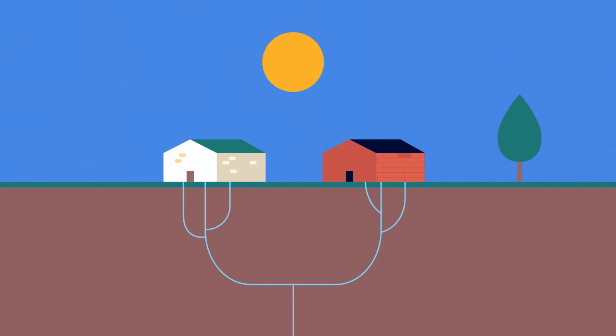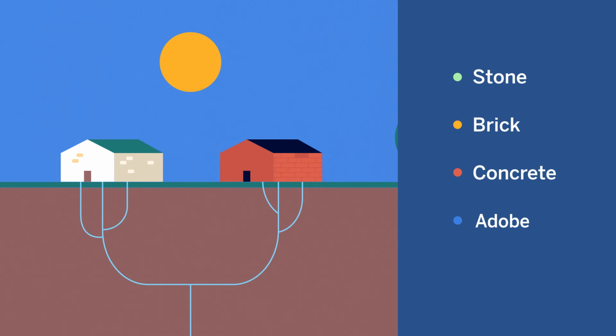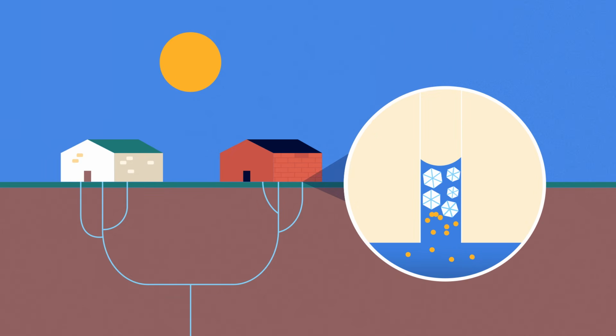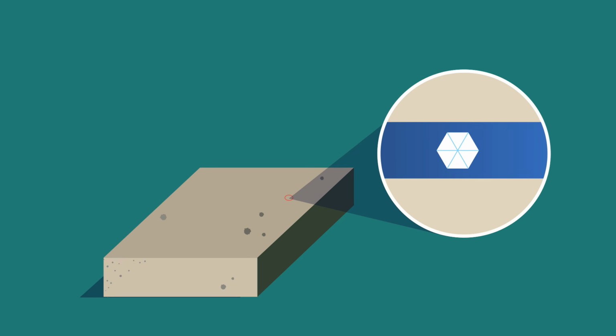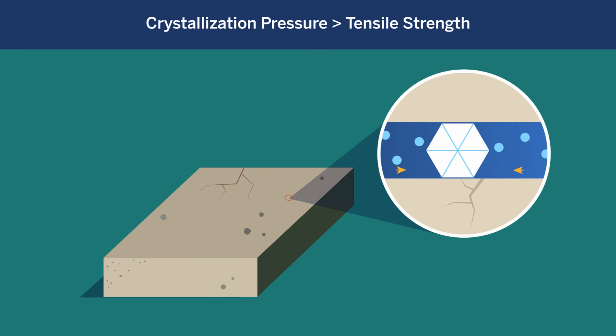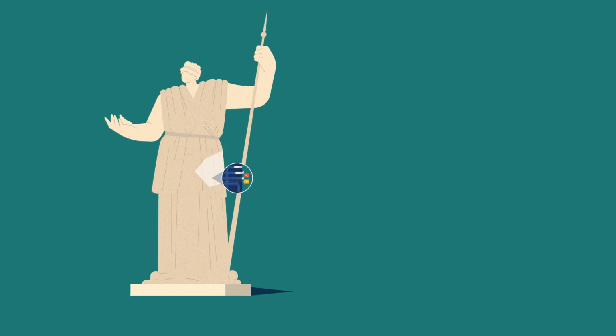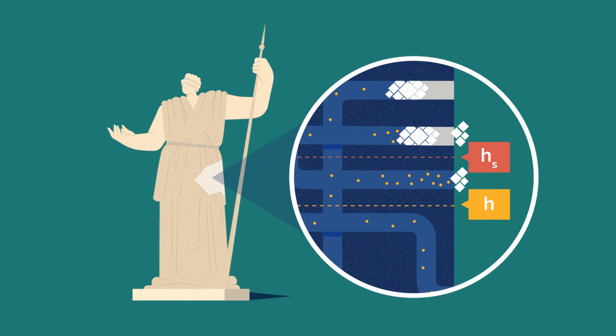In conclusion, capillary rise of groundwater in materials such as stone, brick, concrete, and adobe leads to the precipitation of salts. Damage develops when this happens within the pores of these materials, and the local conditions of supersaturation and salt loading cause the crystallization pressure to exceed the local tensile strength. While efflorescence is not damaging, zones showing efflorescence may also lead to subflorescence because of changes in exposure conditions and must therefore not be considered as perpetually safe.